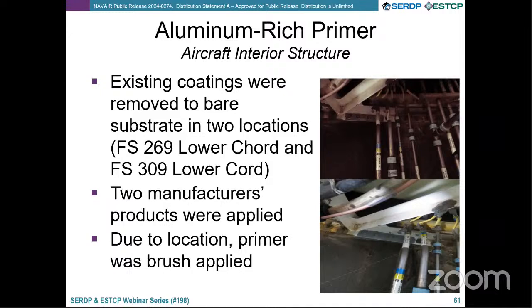Because we're able to show that's exactly why we developed this primer, and that's the type of corrosion one might expect it to prevent - the galvanic corrosion around fastener lines. We've been able to convince a number of programs to let us test the primer on their corrosion-prone areas for the most part. So we started doing that back in 2018 with some particularly troublesome areas for the V-22 program.